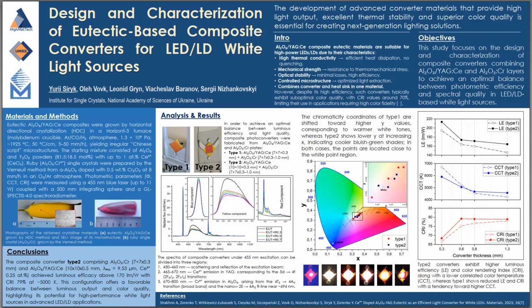However, despite these advantages, these converters still suffer from insufficient emission in the red spectral range. As a result, their color rendering index usually does not exceed about 70, which is a clear limitation for applications requiring high color fidelity.